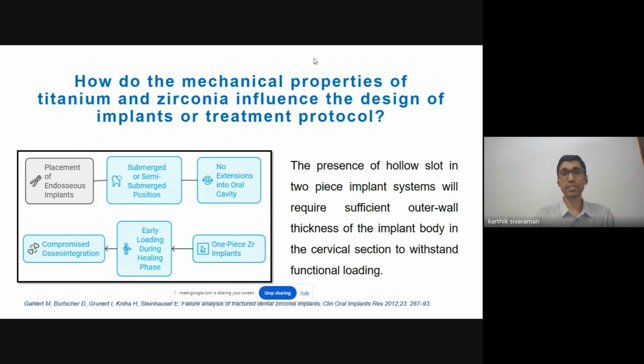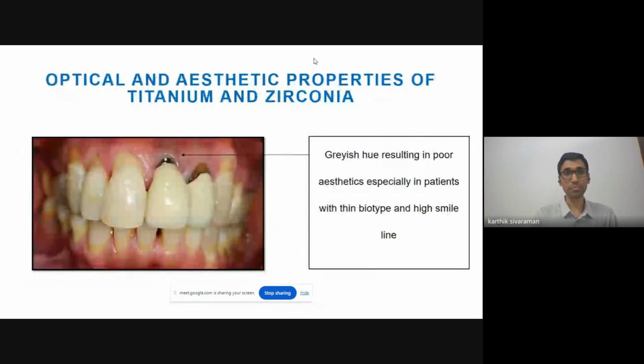Also, when we talk about a two-piece implant, we know that there is a hollow slot in the implant body. Now, when there is a stronger metal like titanium, you can make it in thin cross sections. Or if the bone availability is less and you cannot consider surgical options, there are narrow diameter implants. However, when you consider zirconia, studies have actually recommended against using narrow diameter implants. And since we know that the mechanical property is not as good as titanium, we cannot take the risk due to adverse results.